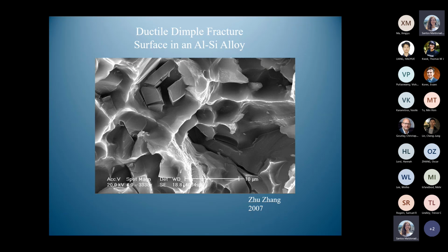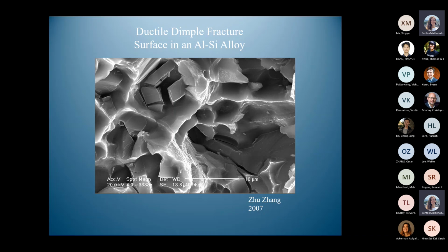which we put into our tensile test machine and just pulled, it would neck down until finally it came away at a point, like a piece of plasticine. And that would be its failure mechanism, a perfect plastic failure. And here we've got perfect plastic failures with all these knife edges around here, whereas here you've got perfect brittle failure, but it's not brittle because the silicon is brittle. The poor old silicon only fractures brittly because it has bifilms all the way through its center.